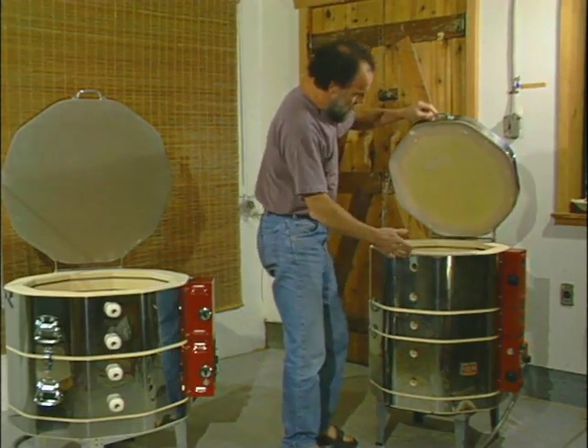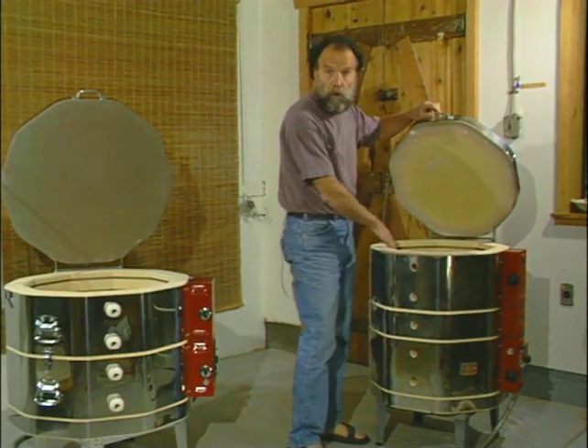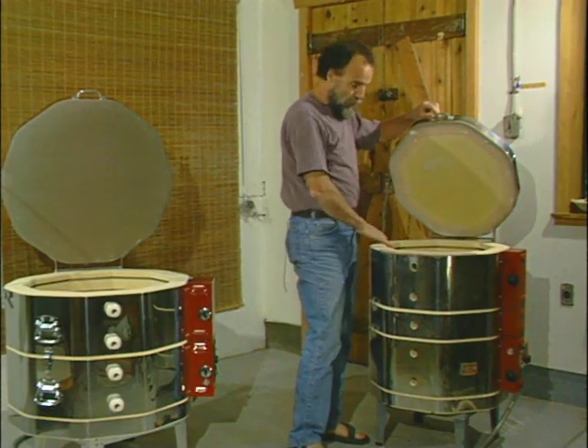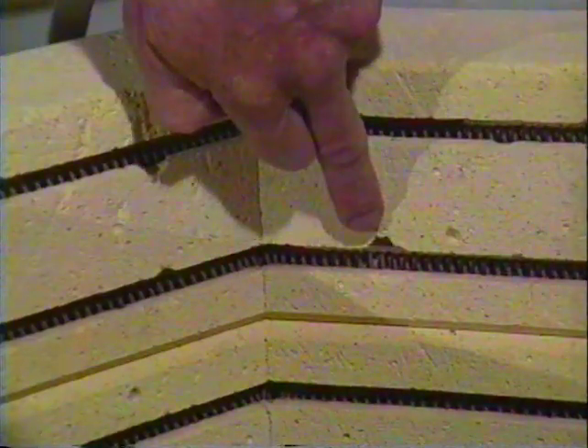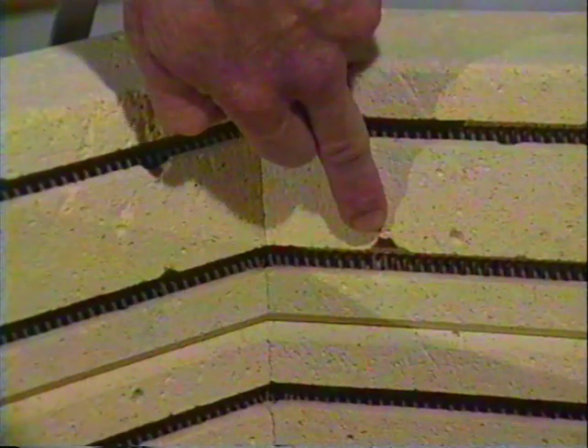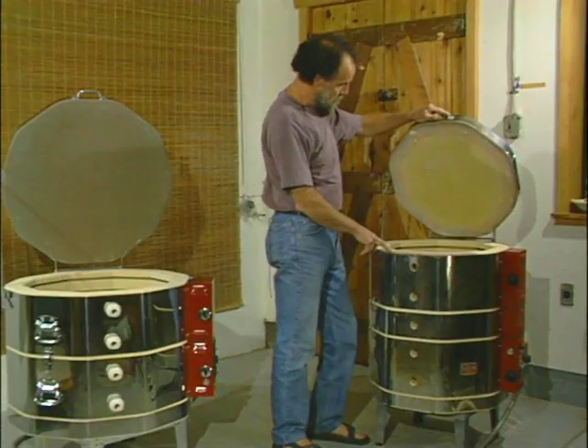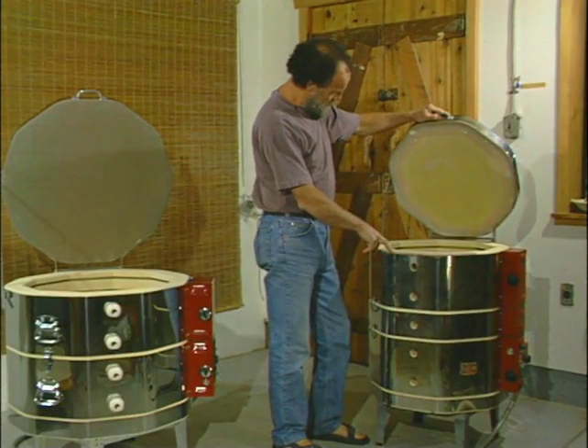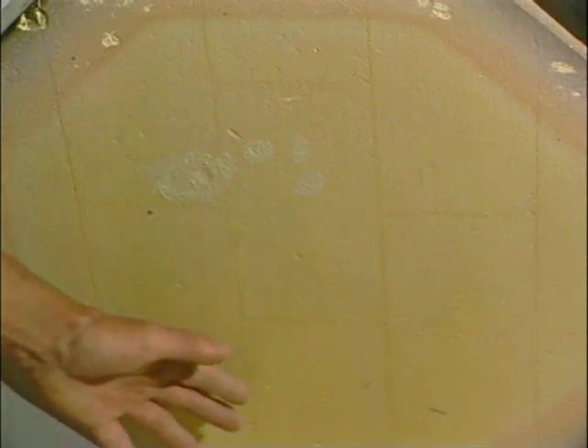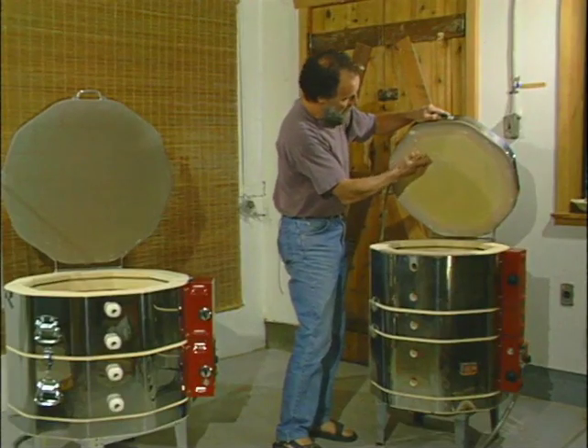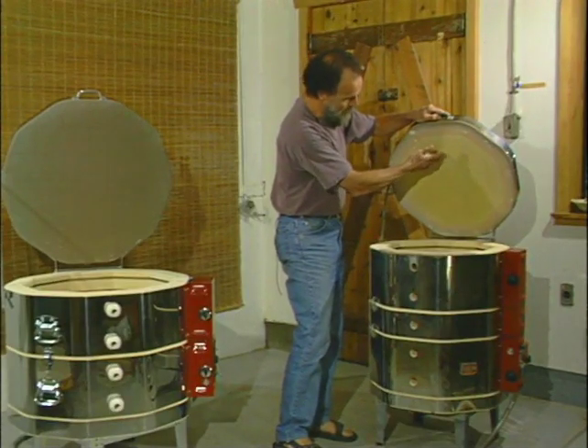It's important also to look at the condition of the brickwork, look at the bricks for soundness. A little bit of chipping that you might see around the edges of this are signs of normal wear. This kiln's about 12 years old and is in excellent condition. Notice that the brickwork of the lid particularly is all very sound. It's difficult to deal with cracks in lid bricks.